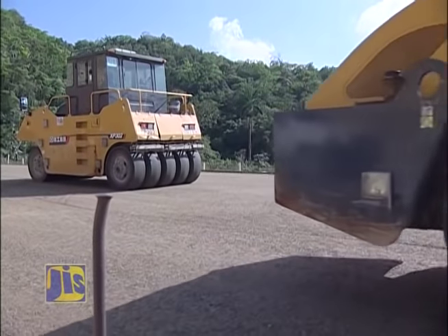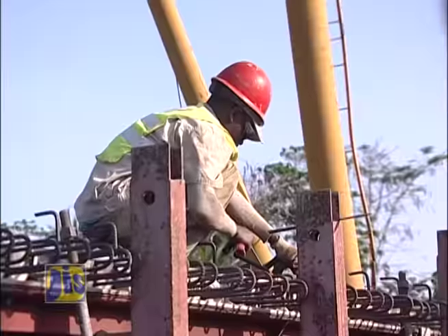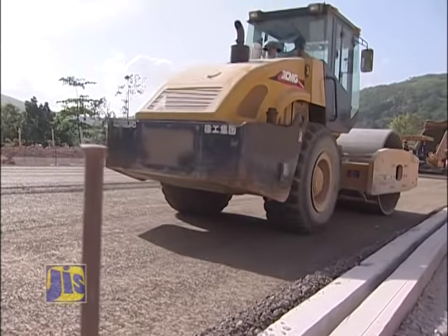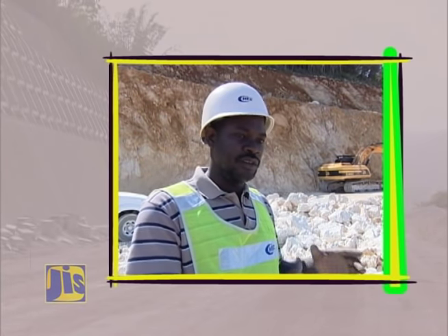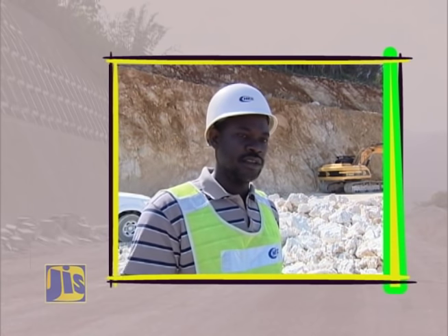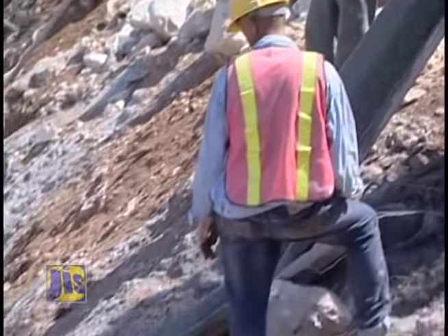Quality control and monitoring is an important part of the construction process to ensure international standards are maintained throughout the highway. Whether it's a bridge, retaining wall, or sub-base of the roadway, strict adherence is placed on structural strength and durability. Every time concrete is poured, they test the strength to ensure consistency. If the strength of the concrete goes below the minimum — for example, 20 megapascals — further tests such as a core test or ultrasonic test are required. If it is not okay, the structure may be demolished.